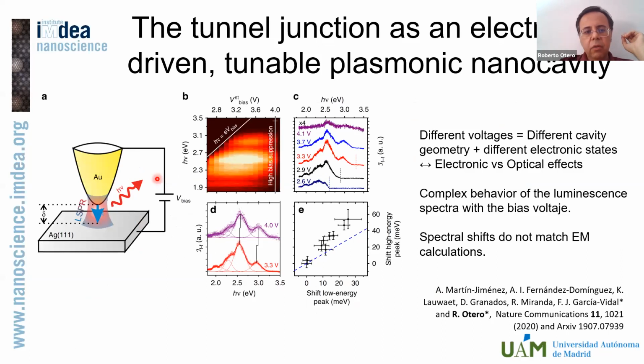This is actually what you measure. So you bring your tip, in our case it's an electrochemically etched gold tip, to a metallic sample. In our case it's a silver surface with a 111 orientation. We bring it, let's say, about 1 nanometer away from the substrate. You inject current, and then some light comes out, and you are able to collect this light as a function of the tunneling parameters. In particular, what I'm showing here is a stack of all the plasmonic spectra as a function of the bias voltage between the tip and the sample.